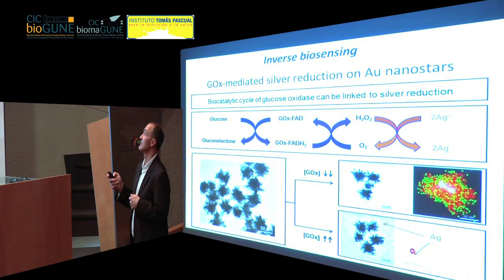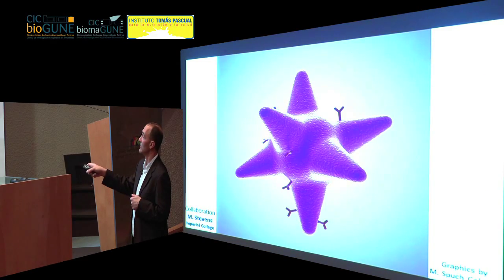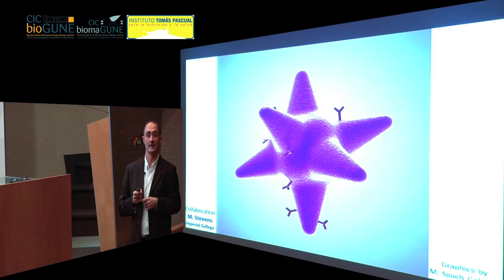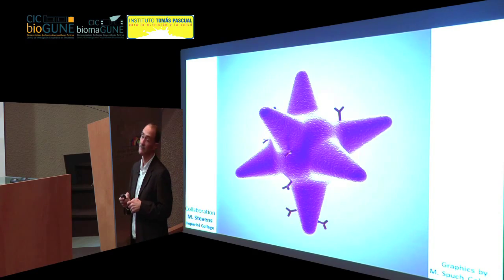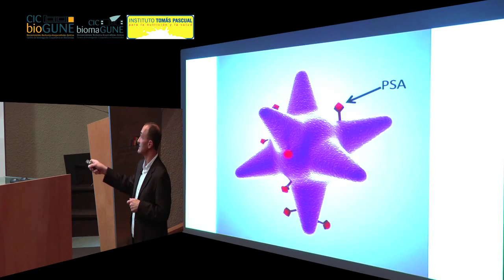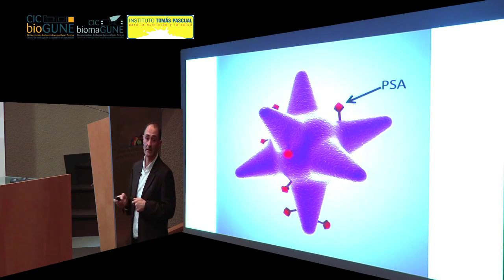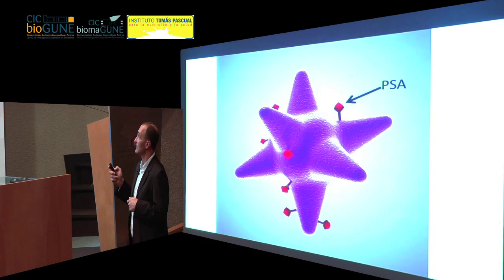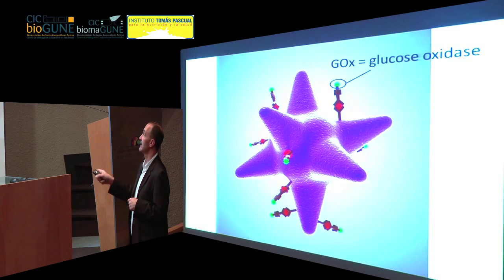Okay, so then Molly came up with the idea, why don't we do this and try to sense something interesting? So we actually deposited some antibody on the surface of the nanostars, which is selective for prostate specific antigen. So in the presence of PSA, it should come and bind here. And then we attach another antibody, which contains glucose oxidase.